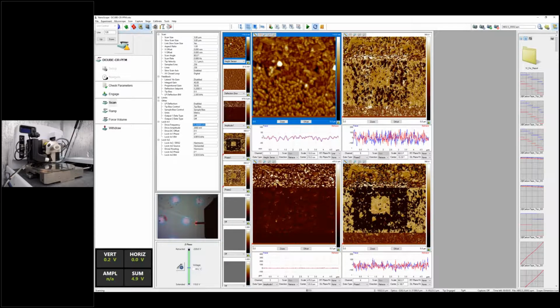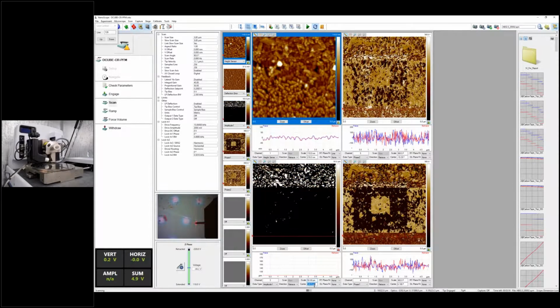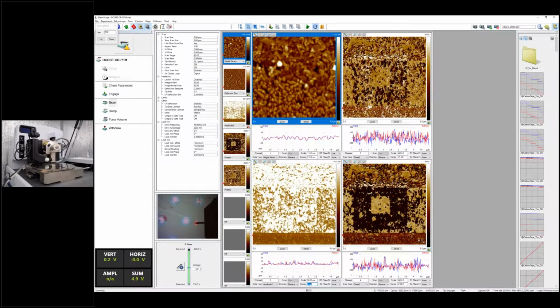So at this low frequency, you still have some signals here. Of course, I need to change the parameters a little bit. For example, I need to lower the bandwidth because we are using a much lower frequency right now. So you can still see the grain distribution, with different grains within the material. And if we change the scale of this one, we still see some piezo response, although it's quite weak. For now, it's about 10 picometers. You can still clearly see the grain distribution from the amplitude.